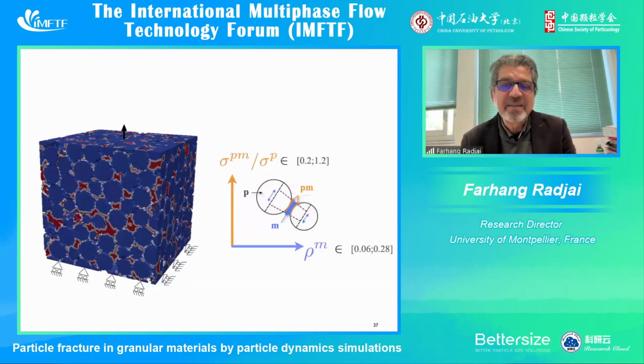We guess that there are 2 properties which control the fracture of these materials. First, the adhesion between the matrix and the particles. So we call this sigma PM. So this is the strength of the interface, let's say. And another property is the amount, the volume of the binding matrix. It's not only the behavior, its role as a binding matrix, binding particles together, but it has also some volume, and this volume, this phase can also transmit stresses. So we studied in a systematic way the role of these 2 parameters.